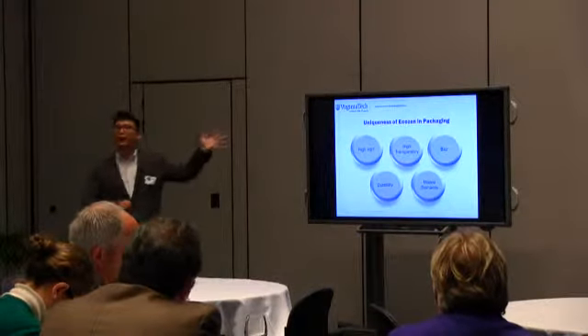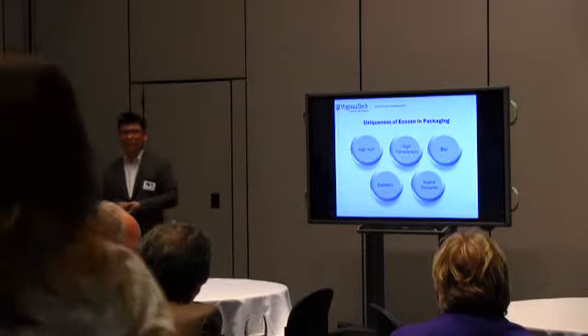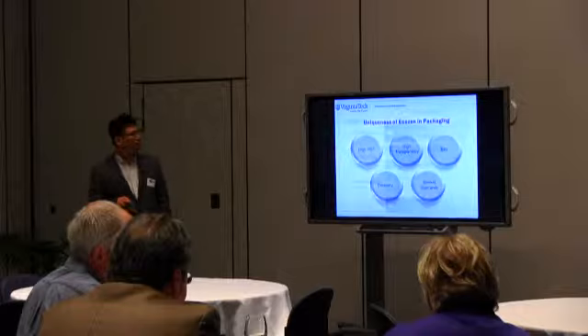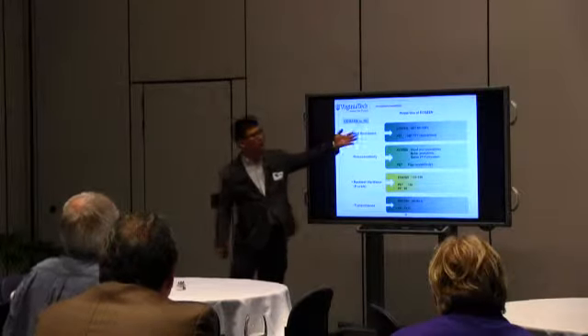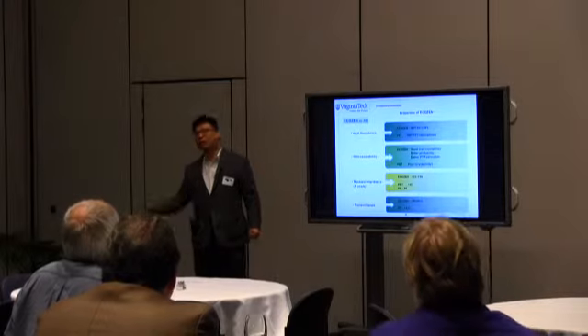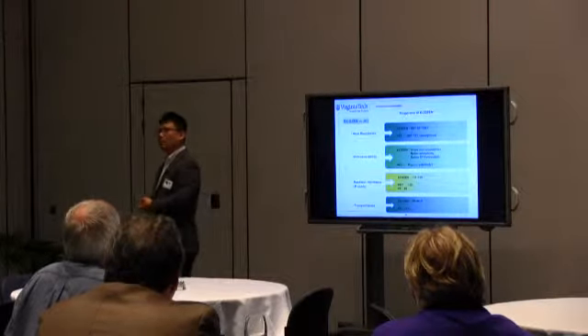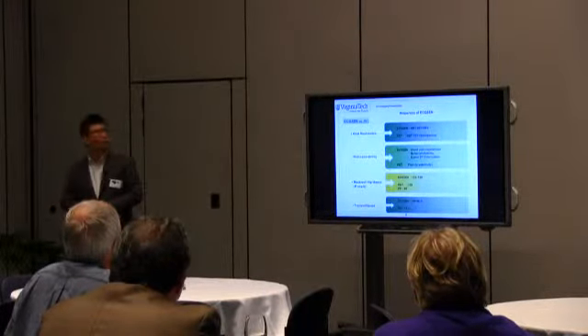In the world, there are two companies manufacturing this kind of material. One is Eastman. Eastman is producing PETG or PETG derivatives. And SK Chemical, they are also manufacturing PETG plus this kind of bioplastic. They are big competitors. Especially for heat resistance, as I told you already, it is okay up to 110 according to the grade of Ecozen. Normally PET HDT is around 70, and 80 degrees Celsius is the maximum temperature for PET.